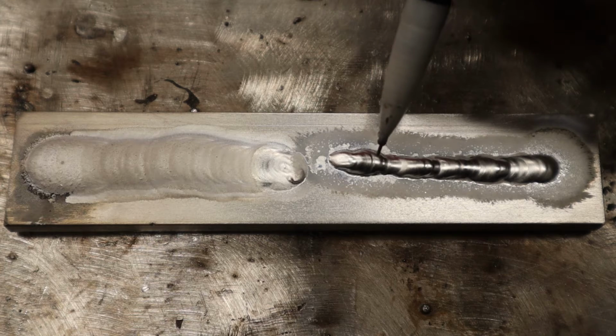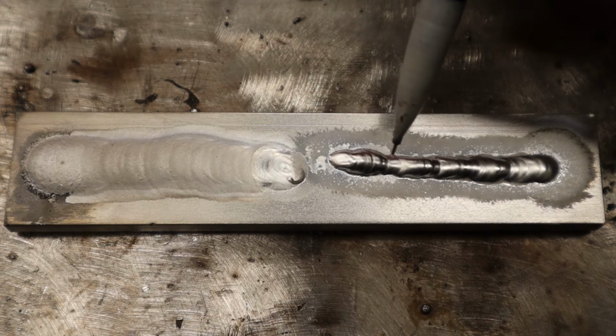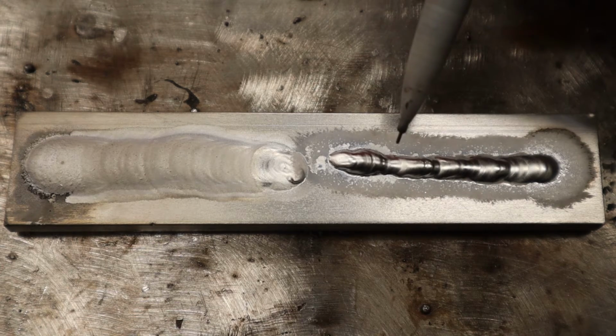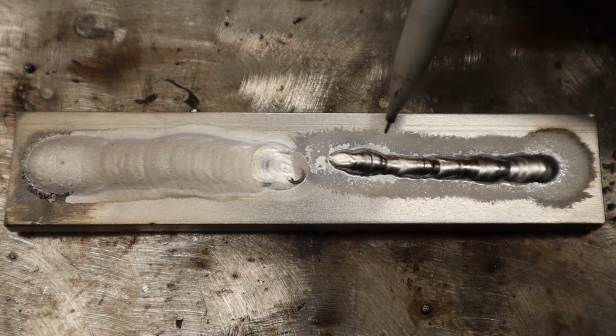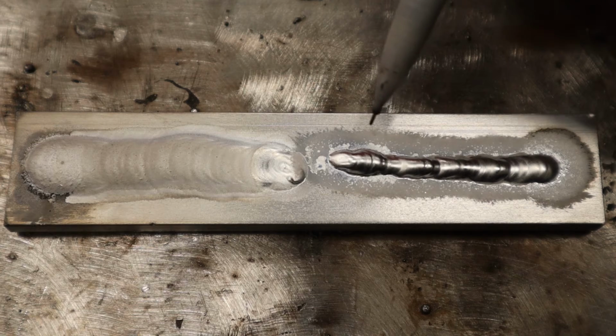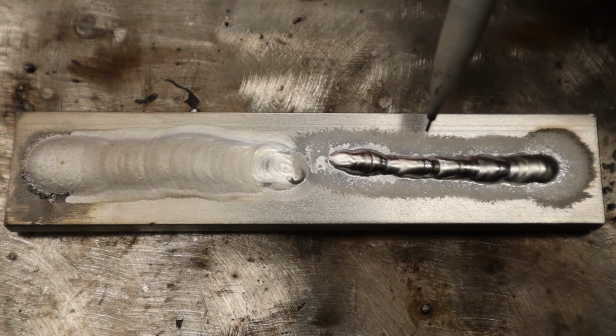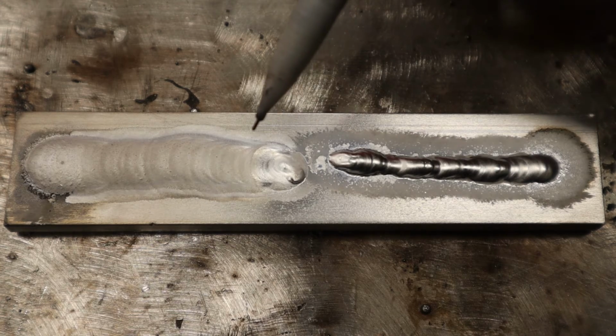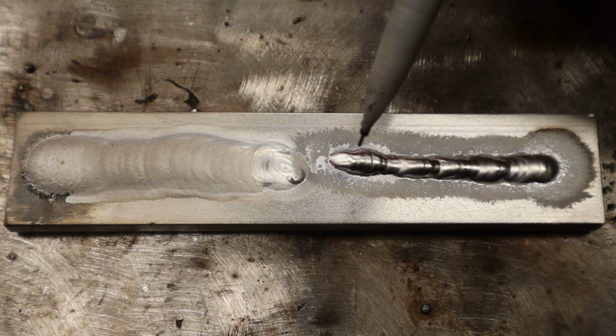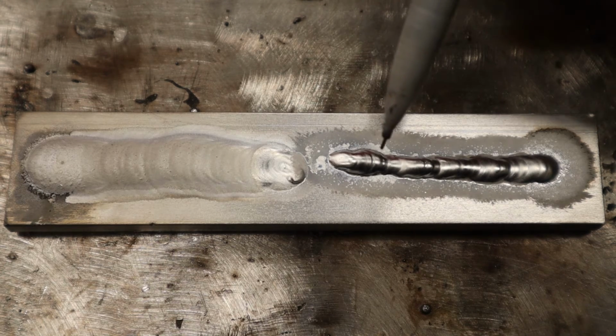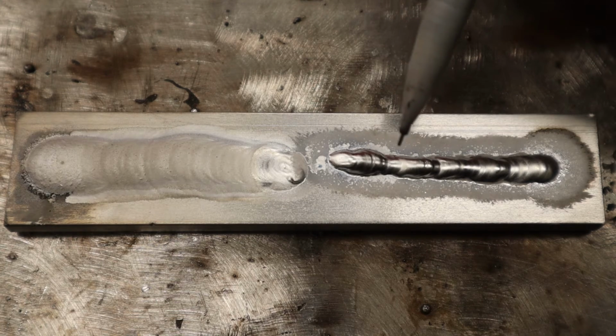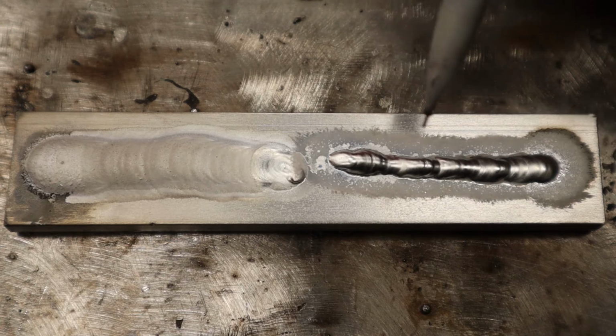Now, with this being too cold, it doesn't smooth out and flatten out. It kind of makes worms rather than kind of circular puddles. So it's very hard to control. In fact, when I was putting the filler rod, it was kind of not even wanting to flow properly and join the puddle properly. And you can tell with both that you actually have a little bit harder time controlling the puddle. With the too cold, it doesn't want to form a full puddle, so it kind of worms up and ties between being solid and liquid.